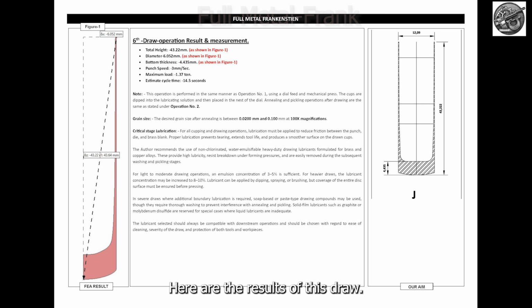Here are the results of this draw. Final height, 43.22 millimeters. Outer diameter, 6.052 millimeters. Bottom thickness, 4.435 millimeters. Cycle time, 14.5 seconds. Punch load required, only 1.37 tons.